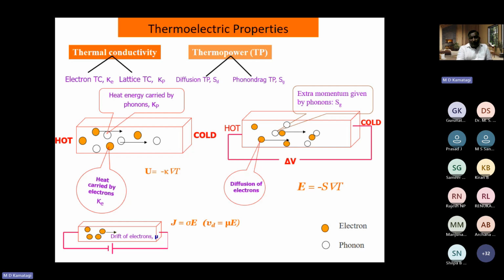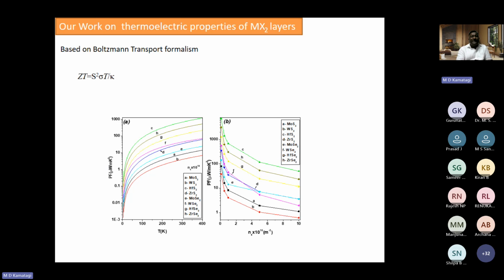What we have done is we have taken a series of MX2 layers and applied the Boltzmann transport formalism. We considered the phonon scattering by boundaries, impurities, and phonons, and electron scattering by acoustic phonons, charged impurities, as well as remote impurities. And we have evaluated the thermoelectric properties, namely thermopower, electrical conductivity, as well as thermal conductivity.